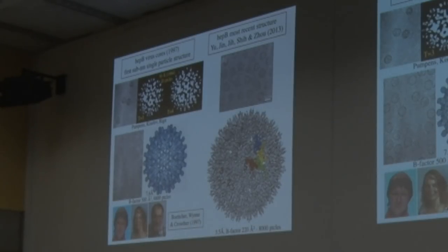And then Hong Cho, the same one who had the higher resolution structure of adenovirus, again took the same specimen, worked hard on it with a new higher voltage microscope, more coherent, but still all these images are on film, and managed to get, with a big particle, easier to find the orientations, a high resolution structure, in which the B factor has been dropped from something like 1,500, and now he's down to 200. And then you'll see other structures where this gets better in time.